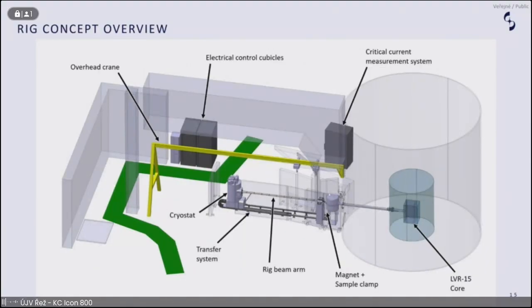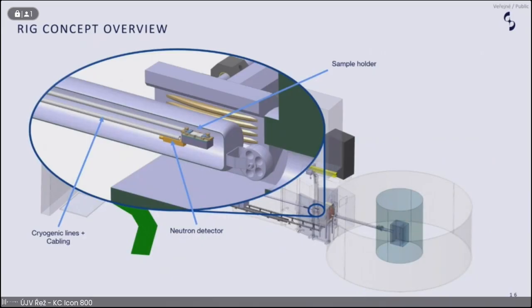This is where our magnet will be placed - we want to apply a magnetic field. There's no way we are putting a magnet very, very close to the reactor core, so we are basically irradiating, then measuring. But because of the ability to operate during those full 28 days, we will be getting sequential measurements during that campaign. What do I mean by that? We will have our sample at the end of the rig arm.